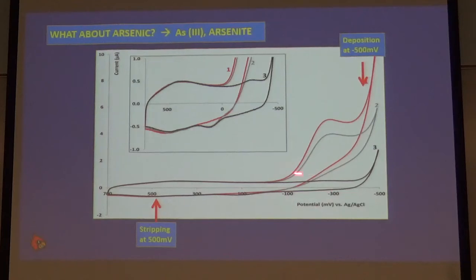But if we do the same experiment and we put arsenic in the solution, we get the gray trace. Now, it still has the oxygen reduction. It's a little different height because it's impossible to control the oxygen content in your sample very well. But you don't see any arsenic reduction. It's buried by that oxygen wave.